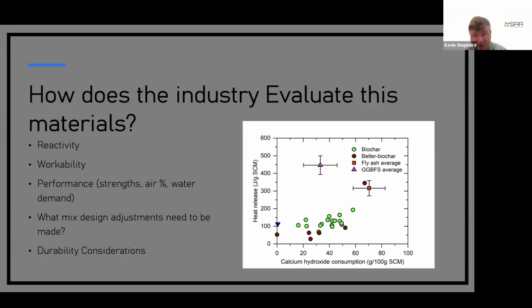We are seeing more biochars test at the 200 to 300 range where you're able to get 20% to 30%. And there are people modifying biochars to get up to the 40 to 50% range. Personally, when I've tested, I haven't seen that yet, but there are claims out there, and you could see with the other biochars that have tested, there is some potential in it.